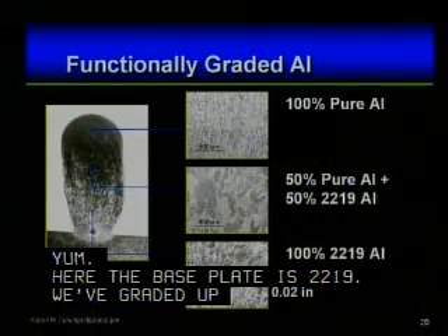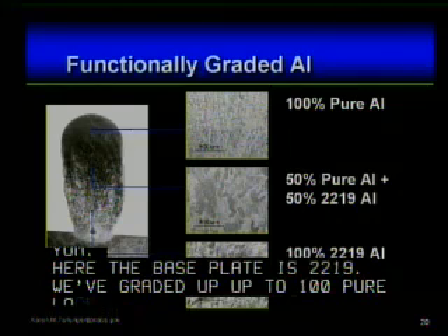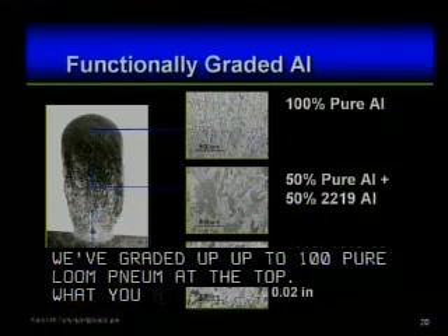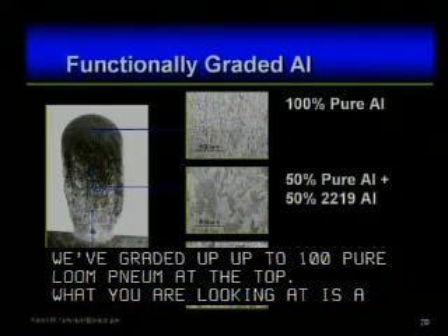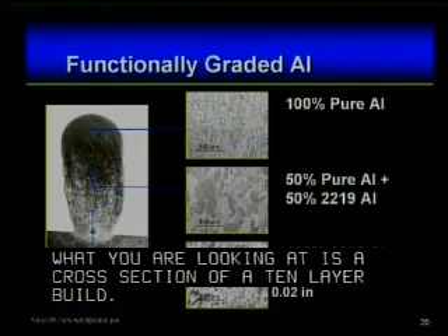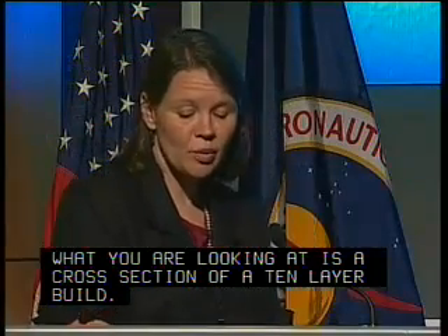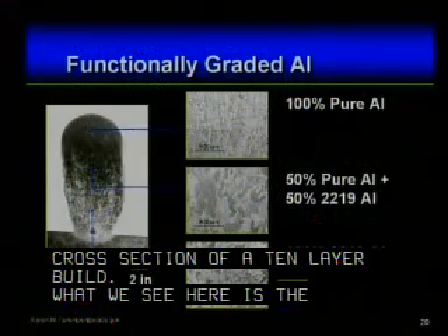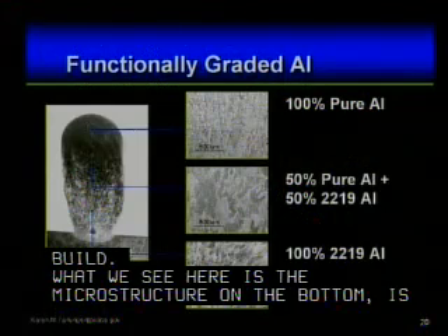So what you're looking at in the picture on the left is a cross-section of a 10-layer build. The first layer was 100% 2219, and then each layer was a 10% change in the chemistry, building up to 100% pure aluminum. What we see here is that the microstructure at the bottom, the 100% 2219, is about what we have seen in the other EBF³ deposited 2219.